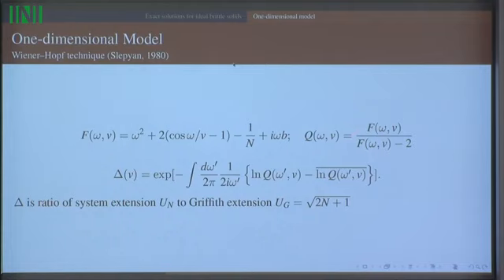You form the following ratio. This is actually related to the dispersion relation of waves ahead of the crack and the dispersion relation of waves behind the crack. So with and without the break, wave motion along the chain, and a ratio of those two dispersion relations. And then a quantity of physical interest is given by this expression, which will look at least vaguely familiar to all of you with experience with the Wiener-Hopf technique.